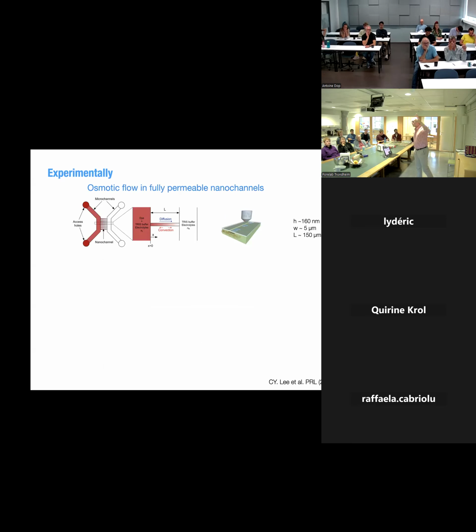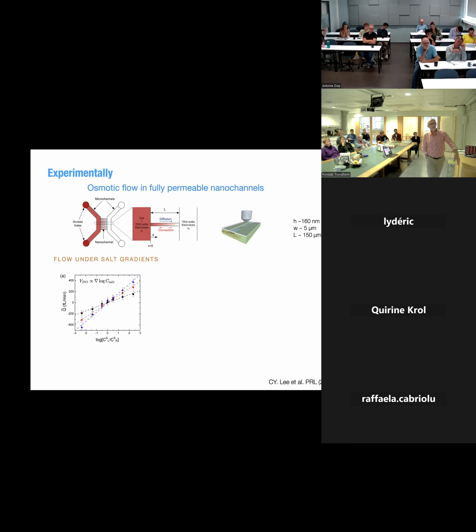Okay, so you have to do it properly in terms of force balance, but that's basically the idea. And some time ago, when I was still in Lyon, we did some experiments just to highlight that. So for example, that's an experiment where you have channels in the range of 200 nanometers, let's say, in thickness. So small, but not very small as compared to the Debye layer, it's very, very small. And we had a way to measure the flow of water. And here it's just to illustrate that for a salt gradient, you have the velocities proportional to the gradient of log of salt concentration. And this works, this is really experimentally shown here.